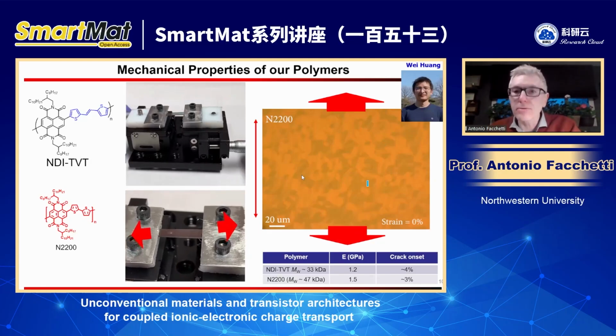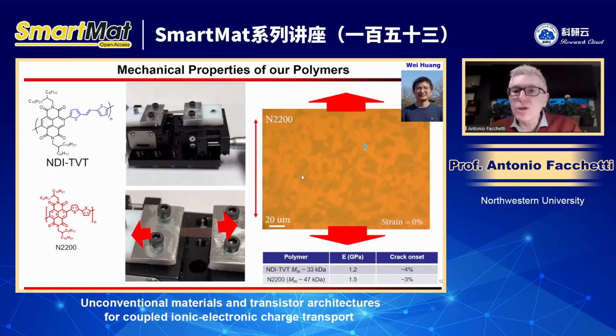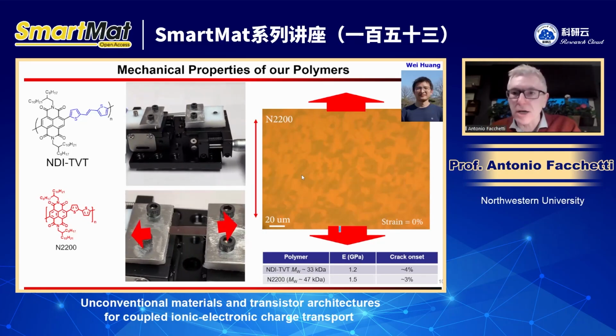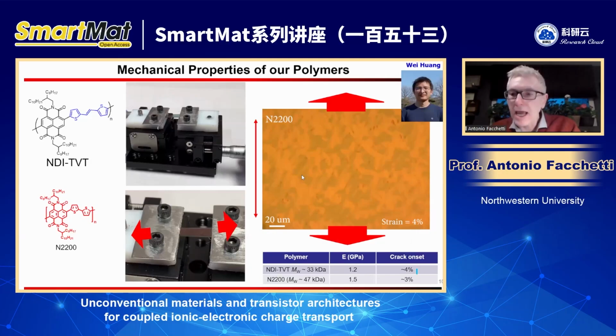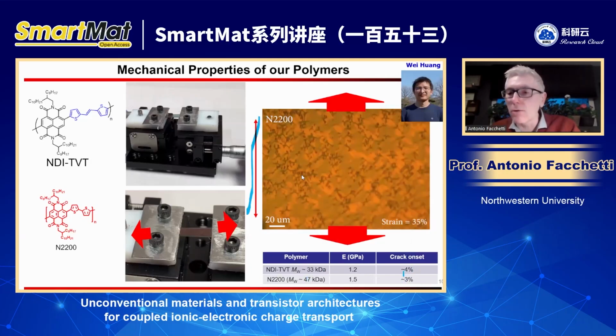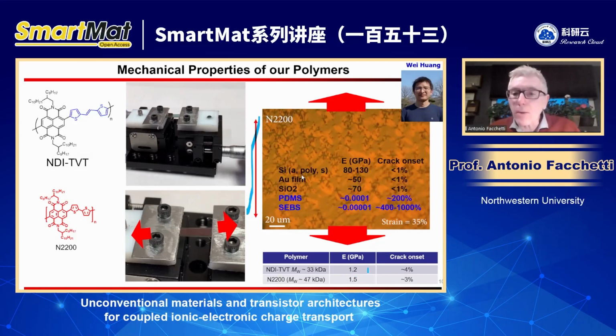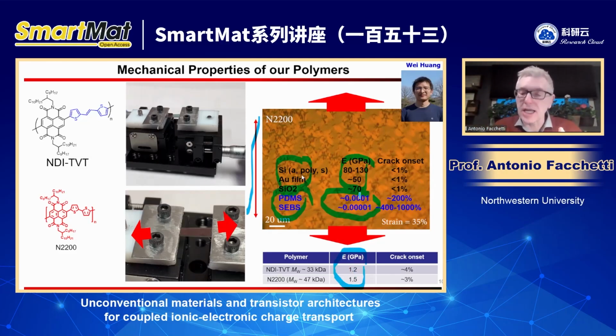If you look at this video here, hopefully it's going to start. Yes, see this black area here, you're stretching in this direction, and you see formation of cracks. The cracks form for both polymers at quite low strain, only 3-4%. This is the Young modulus. If you compare the Young modulus of this polymer versus conventional material, these are much lower. But if you compare to real elastomers, these numbers are very, very large. So you want to lower the Young modulus, and the opposite is for the crack onset. This is very low compared to real elastomers.